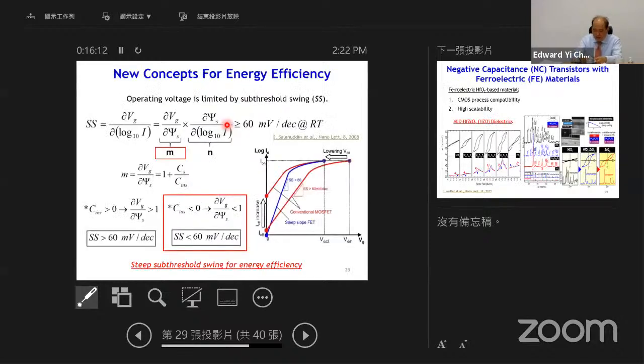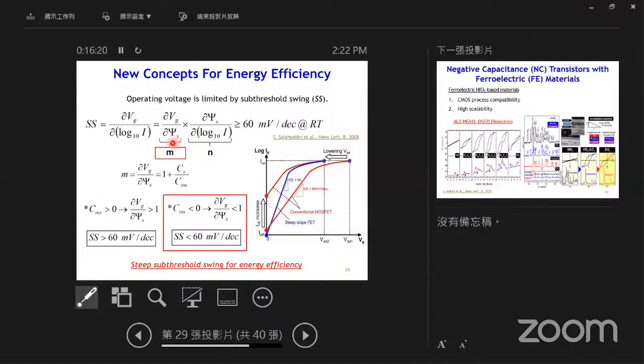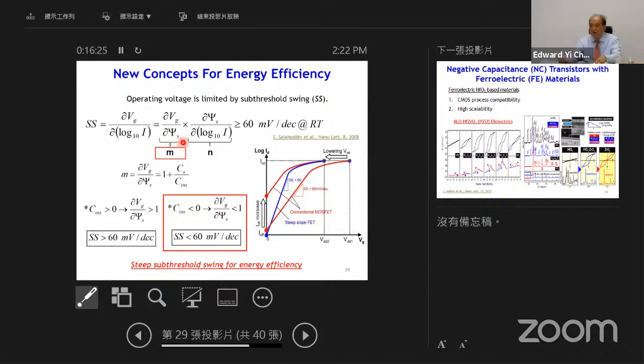Okay, so far I have presented the best FinFET device, and next is how we can improve it. Okay, the way to improve it is... Professor Chang, you have another 2 to 3 minutes to wind up. Okay, sure, no problem. So we further improve by using ferroelectric, so you can reduce the SS, because the ferroelectric changes your surface potential. So you can apply a low voltage, you still create a big potential on the surface. So we can get a very sharp SS, and that means you can bias at low voltage with high current.